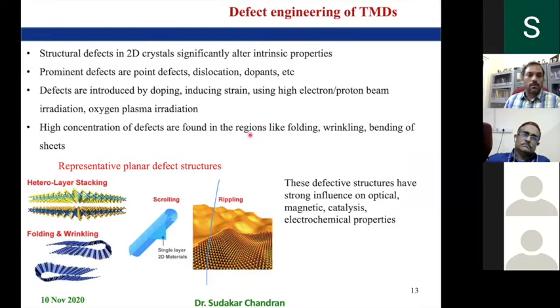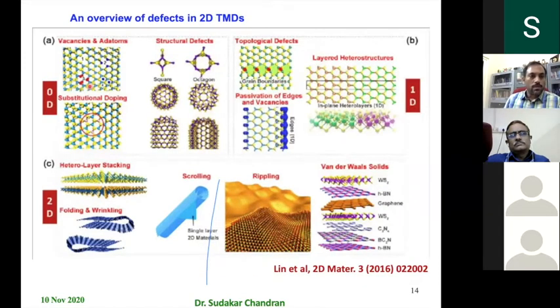In these transition metal dichalcogenides, invariably you get defects. The defects could be of various kinds, okay, and they can alter the properties of the material. Therefore, it is very important to know what all these defects are and how they can influence the properties. The prominent defects are point defects, dislocations, and dopants. For example, if you see this, these are all zero-dimensional, meaning they are all point defects. You have a missing moly or sulfur atom, or some other element can sit at these sites as either an adatom or a dopant atom or substitution atom. That is the zero-dimensional defects.